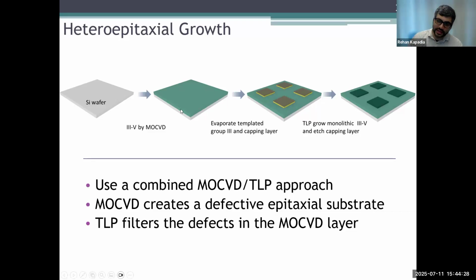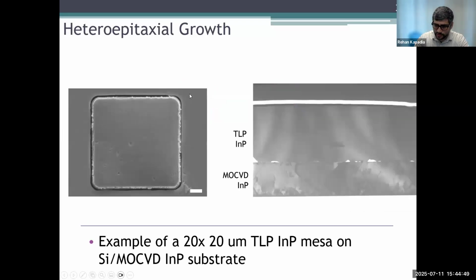We take a silicon wafer, we do a layer of III-V by MOCVD. We'd do our indium evaporation, we cap it, and then we'd grow, say, indium phosphide or indium arsenide or some material in there. I'm mainly talking about indium phosphide, but in general, all of the binary III-Vs are fairly straightforward to do. This shows the surface, but the key thing I want to point out is that on the right hand side, I'm showing a TEM, a transmission electron microscope image, where we have your silicon substrate down here. Then this is the MOCVD layer that we've grown, and then this is the templated liquid phase layer that we've grown.